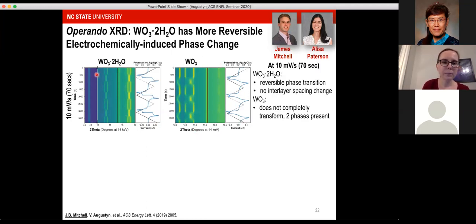So what we see for the hydrous material is this beautiful reversible phase transition that's taking place, this doublet to singlet, doublet to singlet. And again, no interlayer spacing change whatsoever. This material is pretty constant. The anhydrous tungsten oxide at this scan rate never completely transformed. There's always two phases present when it goes through that first redox peak. So that's really interesting, that it never cleanly transforms the way the hydrous material does.